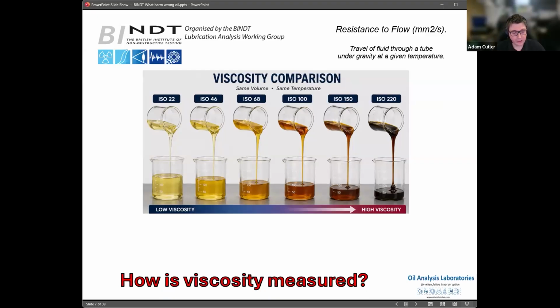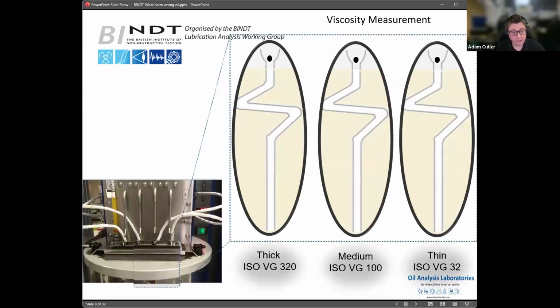So how do we measure viscosity? There are several ways of measuring viscosity, but a common way is kinematic viscosity, where you have an oil-filled bath, and under gravity we drop the oil down one end of a viscometer tube, and it reaches the final point at the bottom under controlled temperature. Then we know by the time it takes to get from one point to the other how thick the oil is.